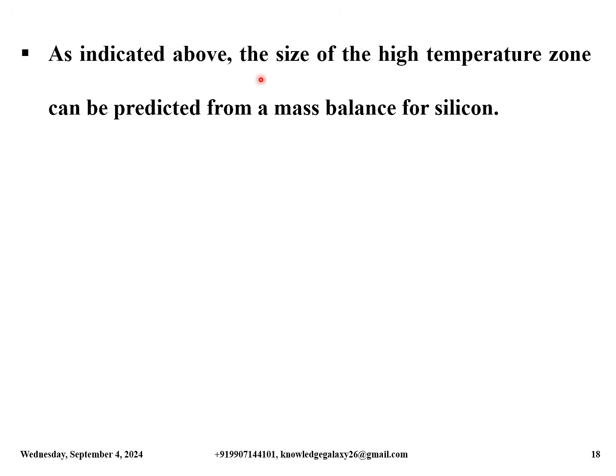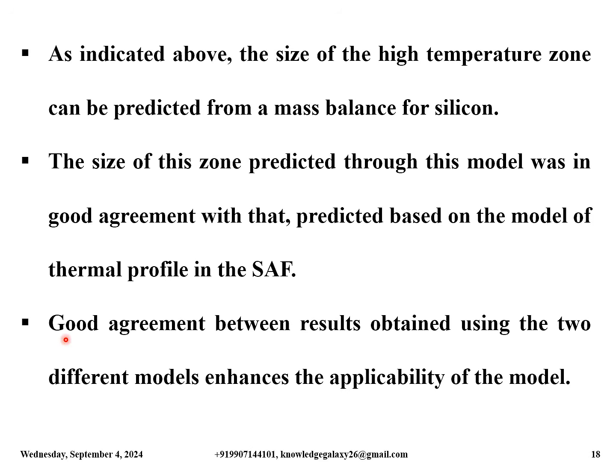As indicated above, the size of the high temperature zone can be predicted from a mass balance for silicon. The size of this zone predicted through this model was in good agreement with that predicted based on the model of thermal profile in the SAF. Good agreement between results obtained using the two different models enhances the applicability of the model.